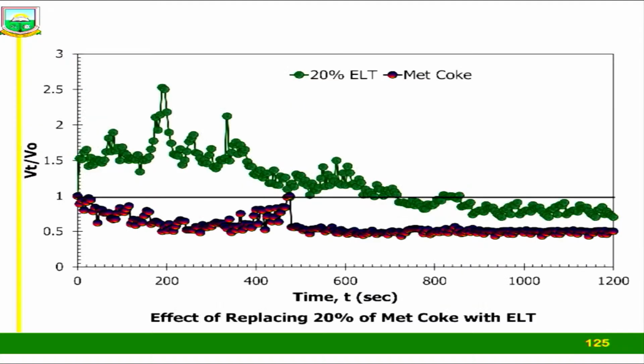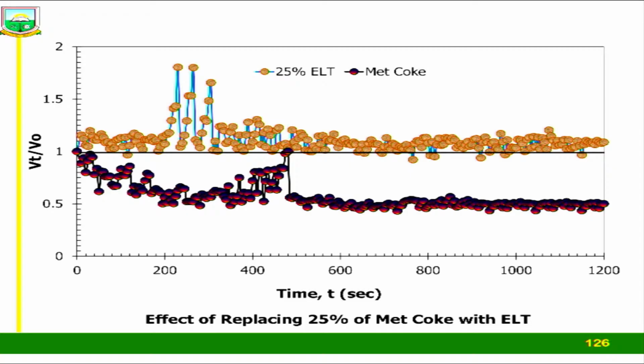By the time we moved from 10% to 20%, what are we seeing? The green graph above the horizontal line is the situation where we have 20%. And we saw that for about 20 minutes, the system was able to undergo continuous foaming, especially up to about 10 minutes, and then it died down. When we went to 25, that is what we got, also perpetually above the line. That was 25%.